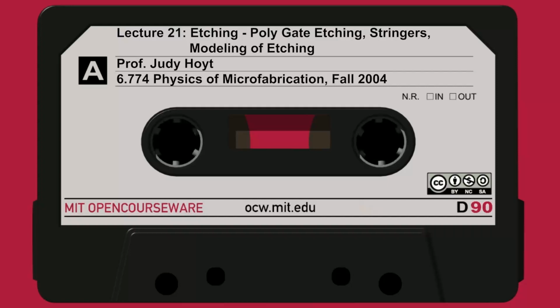So you will see the topography on modern devices, as they get smaller and smaller, everything has to be smoother and smoother. That's why people went away from LOCOS, right? LOCOS creates this big hump on the wafer. People don't like that. We do shallow trench, which creates a perfectly flat wafer. That way I can pattern a very, very fine line and I don't have to worry about stringers.